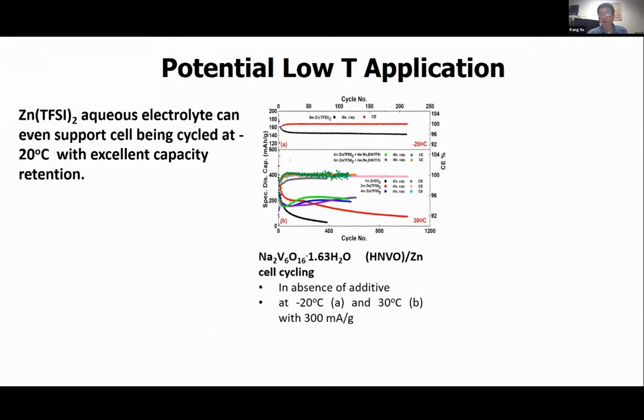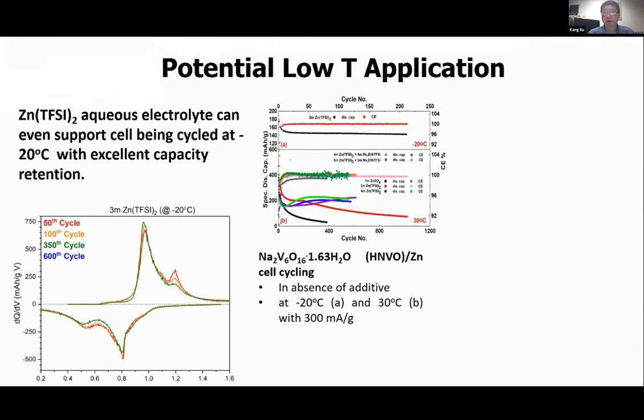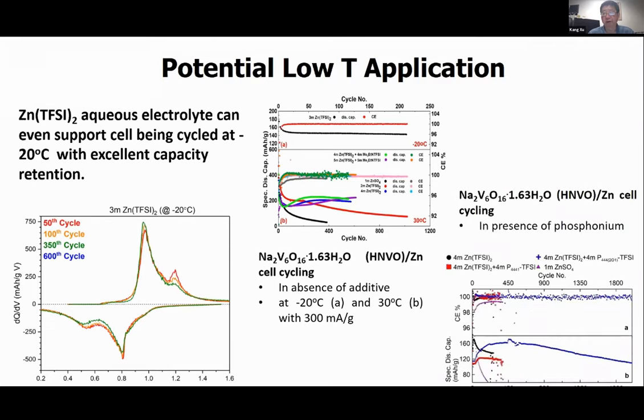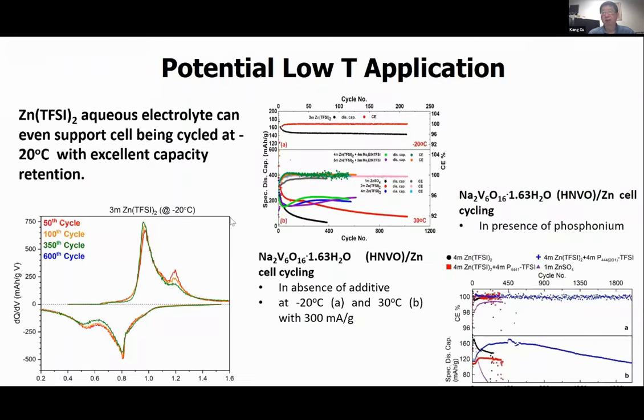But it's very encouraging. I mentioned before that from the phase diagram, you can see that the zinc TFSI or zinc OTF aqueous electrolyte can actually support cell operation at very low temperature. So in this case, we borrowed one cathode material, which is hydrated vanadium oxide. We found that even at low temperature, minus 20 degrees C, the dQ/dV data plotted from those constant current cycling are very close to each other, almost identical, for the different cycle numbers.